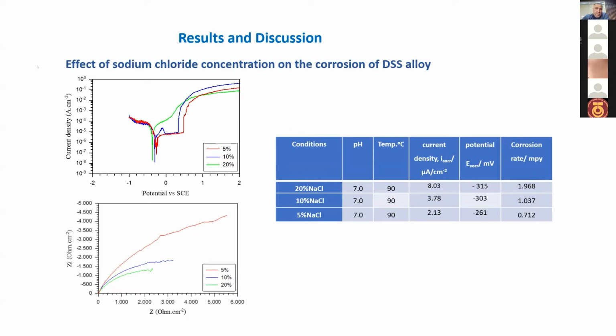Now we see the potentiodynamic polarization curve, and the data in this table deduced from this curve indicate that the increase in the chloride concentration leads to a significant increase in the corrosion current density and the corrosion rate. As we show here, the corrosion current density increased from 2.13 to about 8 microampere per centimeter square, and the corrosion rate increased from about 0.712 to 1.9 millimeter per year when the chloride concentration increased from 5 to 20%.